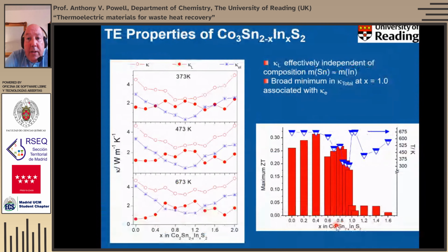Our thermal conductivity doesn't really change very much in terms of the lattice contribution, and that's not surprising because the mass of tin and indium are almost the same. They're right next to each other in a periodic table. But we do get a broad minimum in the thermal conductivity as we approach that 50-50 mixture. The 50-50 is at the lowest point here. We get a broad minimum due to the fact that the electronic contribution shows a minimum at that point because, of course, that's where the resistivity is highest.